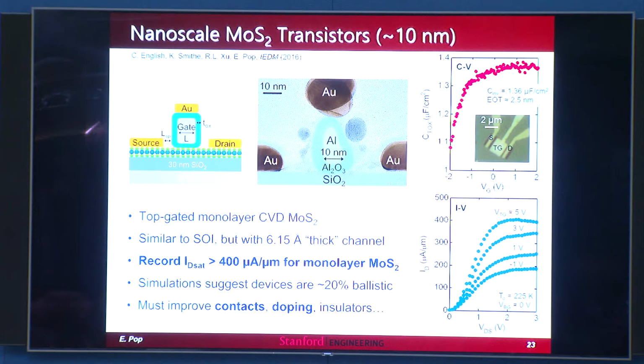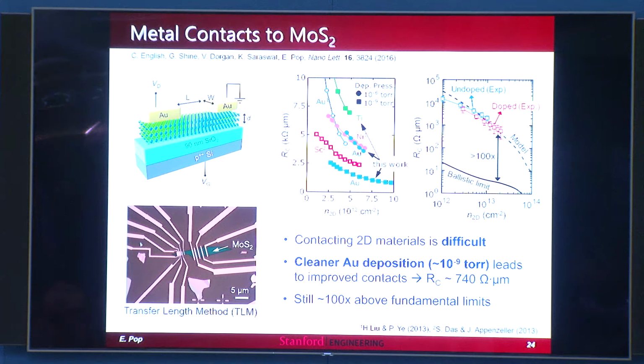The devices were not as ballistic as we had hoped, and that has to do partly with the contacts and partly with the mobility, which is not quite as good in this material, and the effective mass is a little bit heavier. So those are things to be worked upon, and especially from an engineering point of view, contacts and doping are really big bottlenecks for us. Speaking of contacts, our contribution in the contact field for these materials is fairly simple, but it turns out practical. We basically had access to multiple metals and multiple evaporators at Stanford.